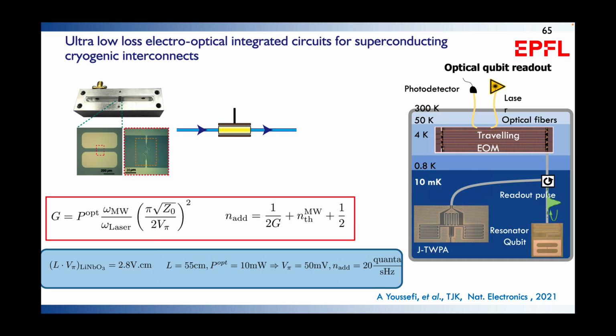What you need to achieve to do that is one element, which is the optical modulator that will take the RF signal from the superconducting circuitry. The qubits operate typically at 5 to 10 gigahertz. But in order to convert that to an optical signal, an optical modulation, you need an exceptionally efficient optical modulator. To replace a conventional HEMT amplifier, you need to operate with switching voltages well below 100 millivolts. So this needs to be a modulator that you can switch basically with your heartbeat.